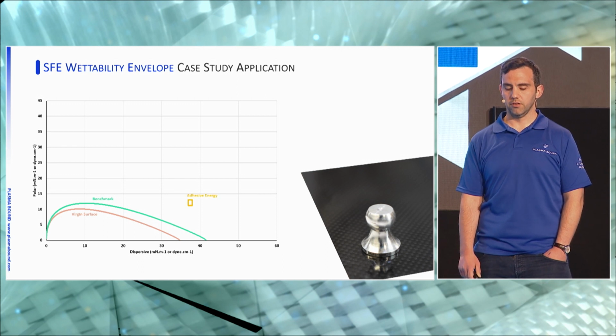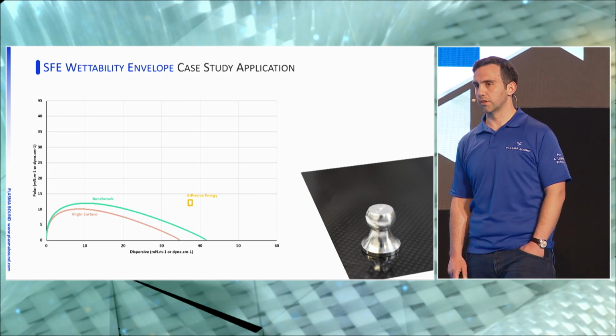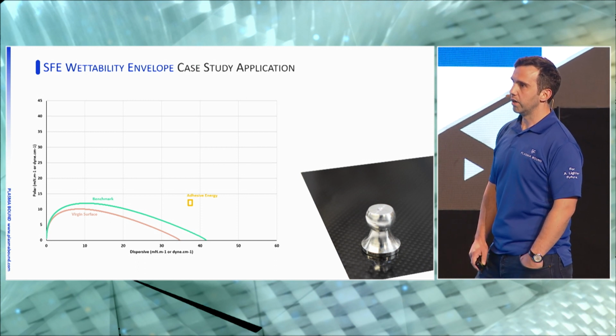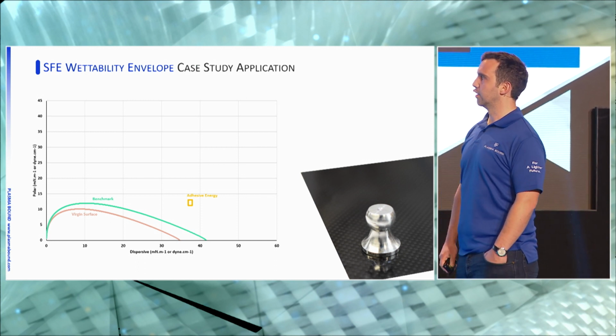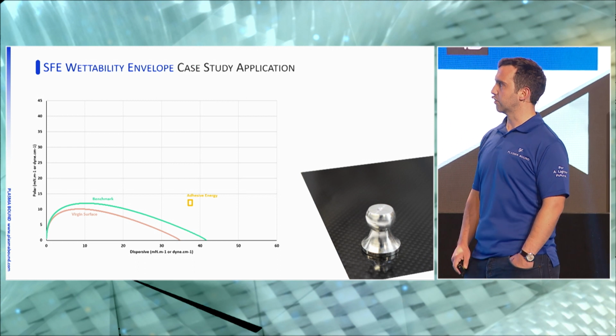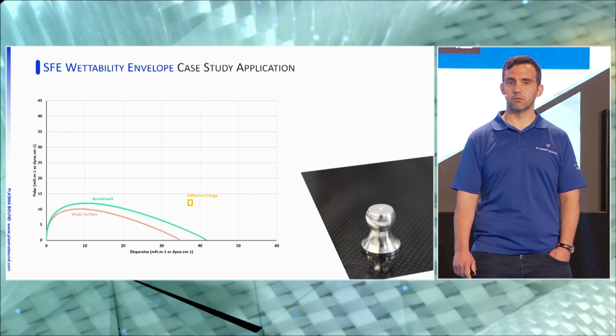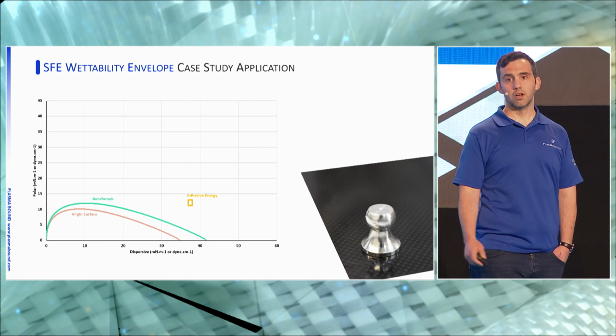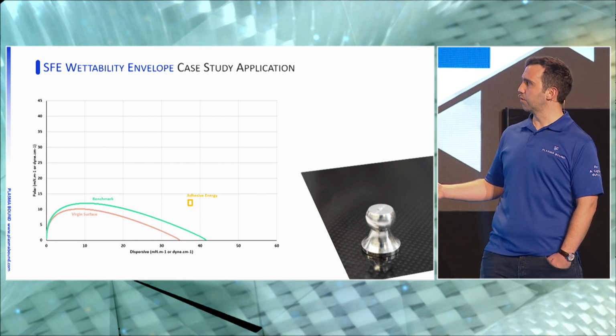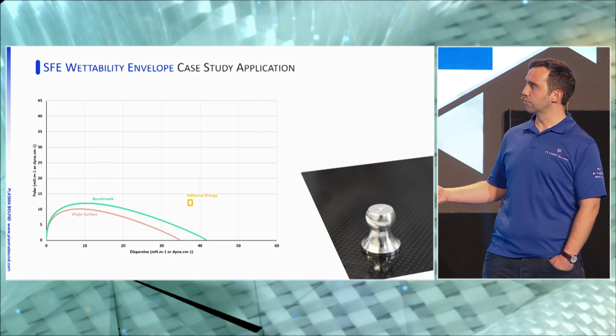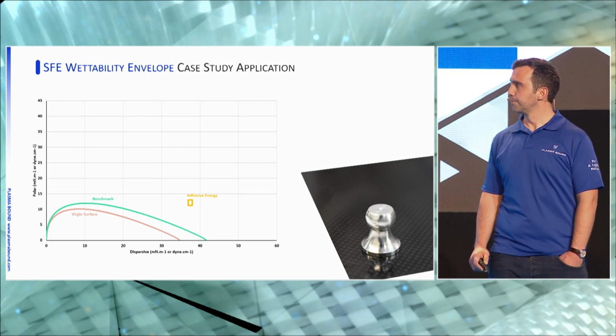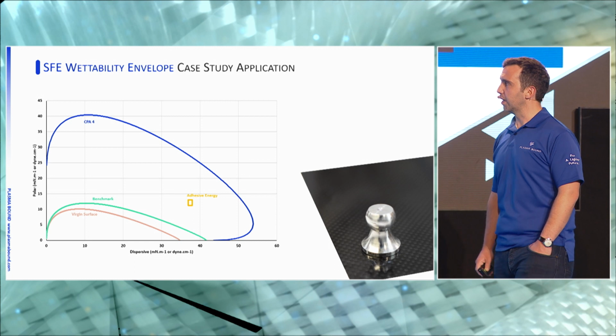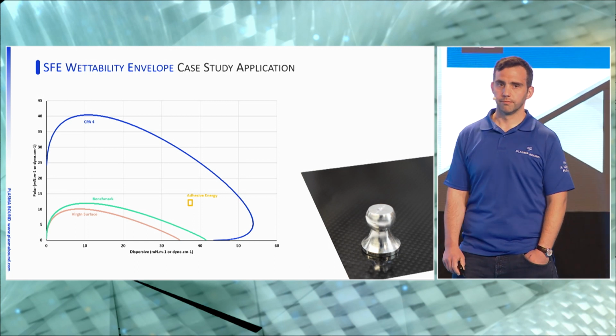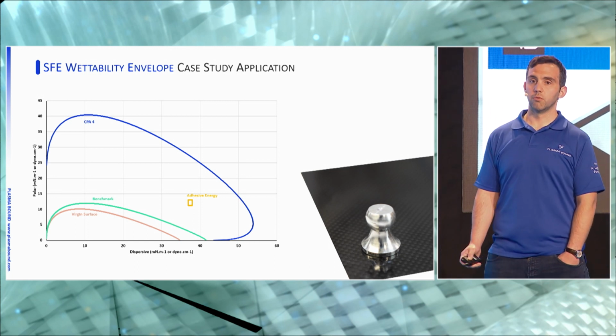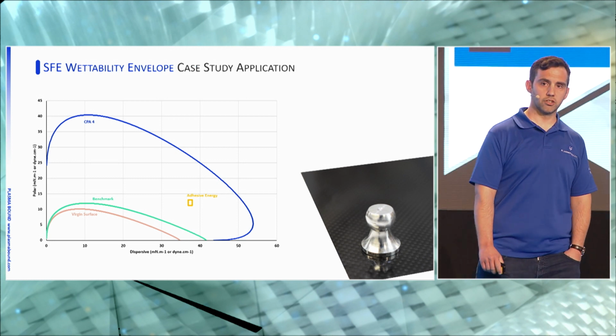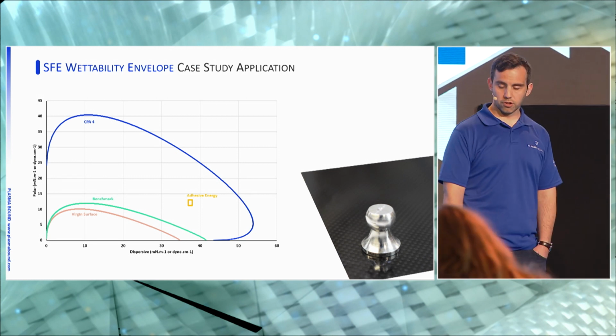And then they sent us their adhesive, which we evaluated and found it to be miles outside of their envelope. We weren't surprised to find out that essentially the reason why they were contacting us is because they were having reliability issues. Some days it would work, some days it wouldn't. The reason is often you will find that when the envelope is outside here, you will get sometimes good bonding, sometimes not. In the case of CPA, this was the envelope we generated for them. So essentially, we did away with the concern that they had about the reliability.